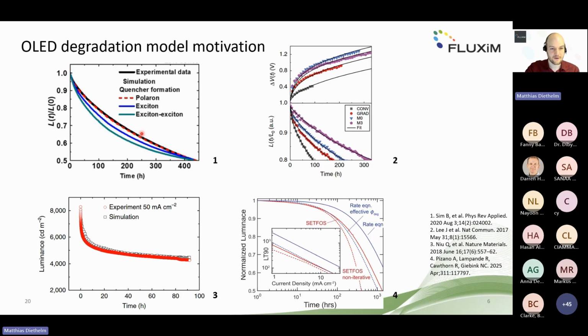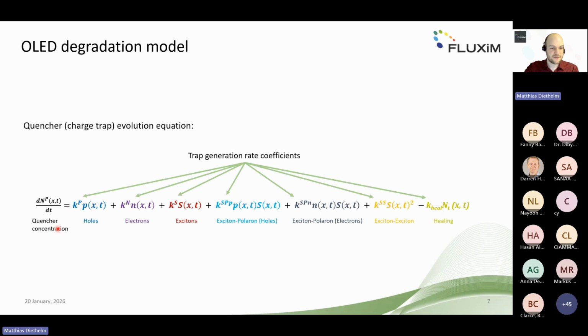You have here the luminance decay at a constant current, and you can see here several examples of how different models, either analytical or also a full drift diffusion model, were applied to understand this degradation in OLEDs. And the core of these models is the evolution of the trap or quencher concentration with time, and also laterally or through the device, with which results of different processes. You can see here you can either have just a simple trap site generation from the whole profile or electron, but what's mostly looked into in OLEDs is this exciton polaron quenching, where the exciton is quenched due to the hole density.